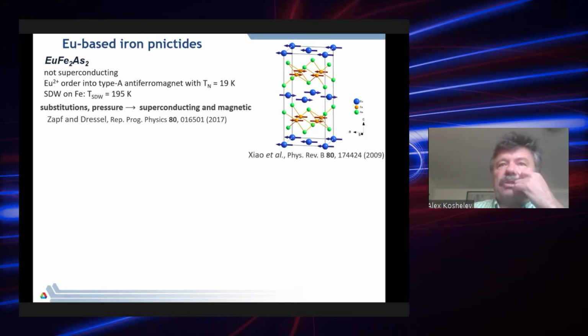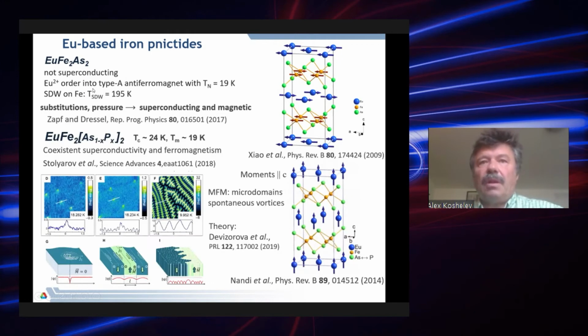Belonging to the same family is also a magnetic superconductor. Instead of barium, one can use europium, which has a magnetic moment. And in addition to the spin density wave state, there is also a magnetic transition related to ordering of europium moments in the europium sublattice. Also, the parent material is not superconducting, but again, it can be driven to become superconducting by either pressure or multiple substitutions on every atomic site. And the most studied material in this family is phosphorus doped, where arsenic is substituted by phosphorus.